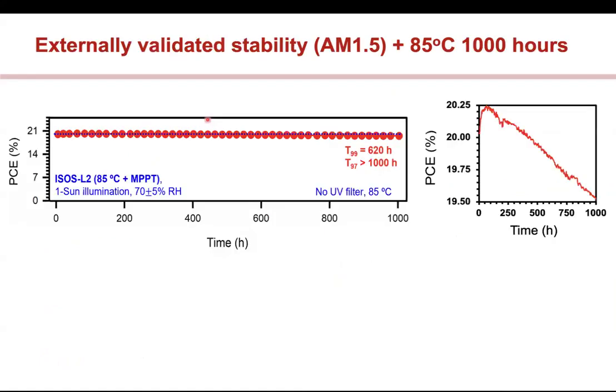But most importantly, you get this stability, right? So this was externally validated. This is a cell which was run at 85 degrees C at maximum power point tracking. And you can see that this device is extremely stable now, right? And you get very little degradation. And so this was really the first report of getting this type of technologically relevant or commercially relevant stability in these halide perovskites by using 2D as your templates.